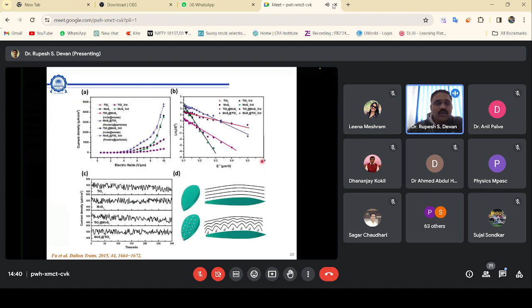And that led to lower field emission properties. So here, the field required to emit a current density close to 10 microampere per centimeter square was much higher. And that's the reason this idea was dropped.